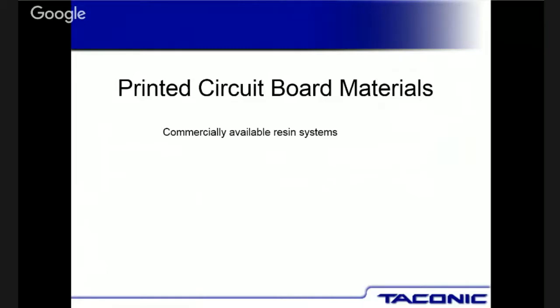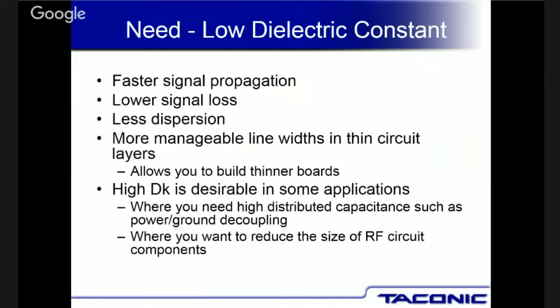One of the big things that we look for in our industry is the dielectric constant of the material. The dielectric constant of a material really determines how fast the signal is going to propagate on the board, how fast it's going to get from point A to point B. The lower the dielectric constant of a material, the faster the signal will propagate down the trace. So we want faster signal propagation, lower signal loss. By picking an impedance that you're going to use on the board, you can determine that a 50 ohm line is going to be X mils wide, and you're going to have a nice clean signal.